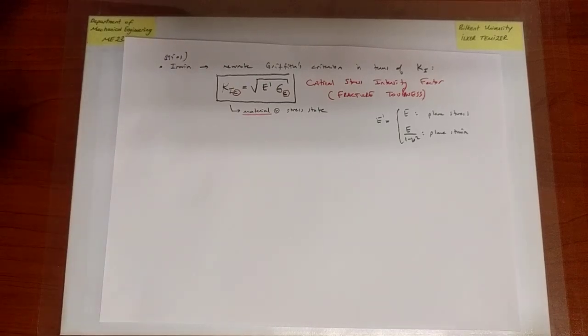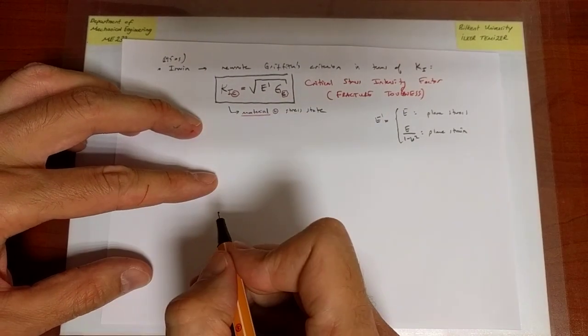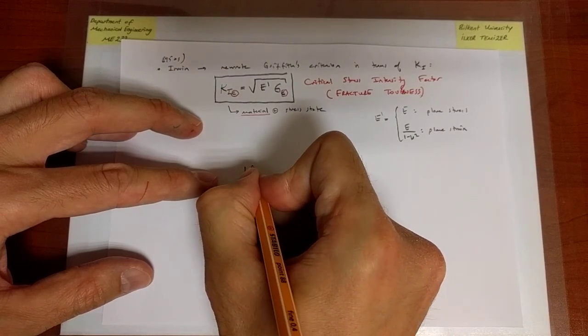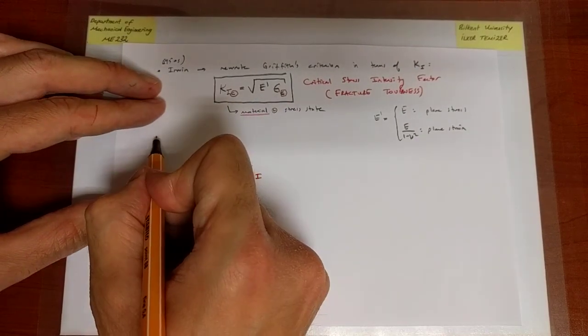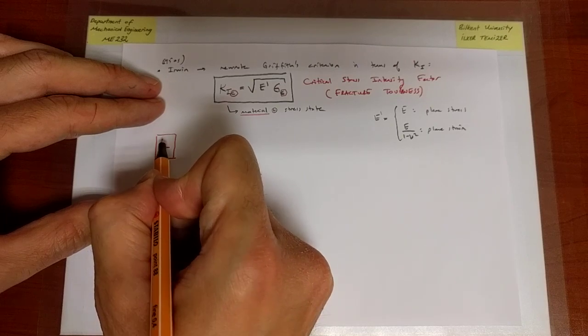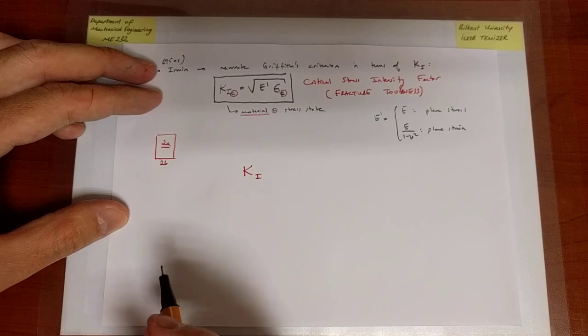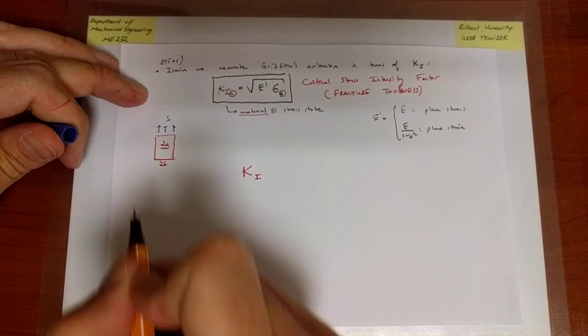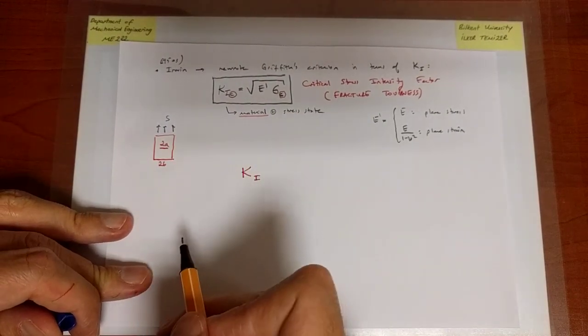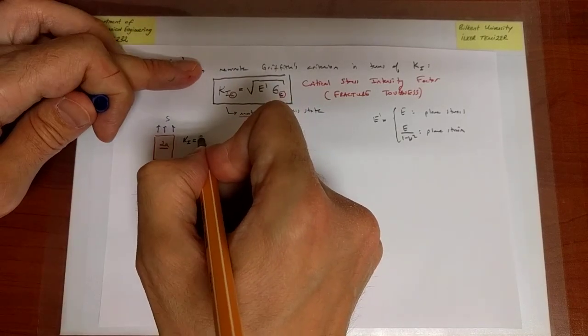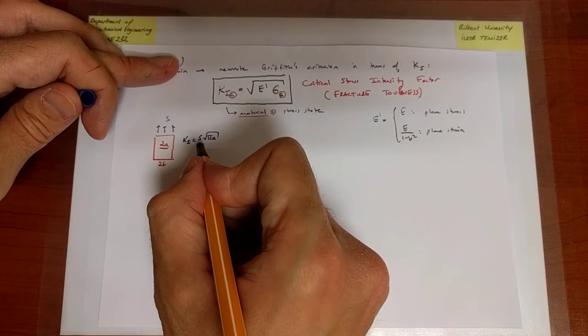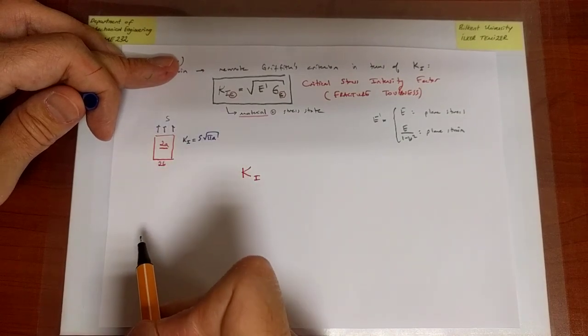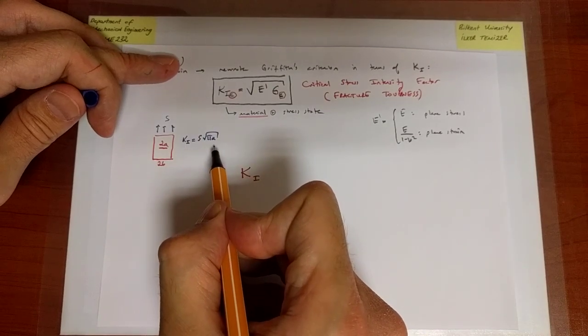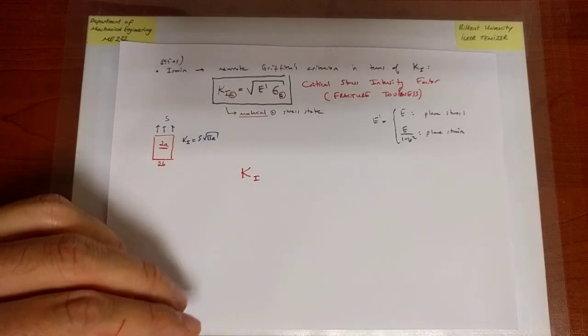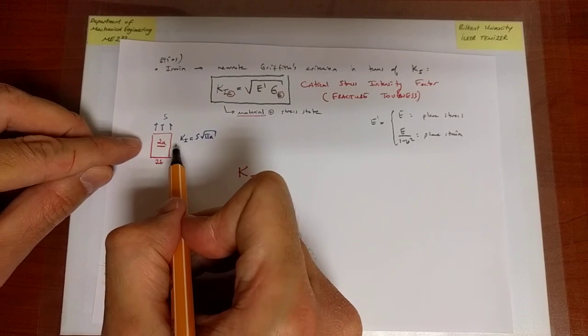So now, what Irwin said is, would you like to predict whether or not fracture occurs? Very simple. You give me the structure, and for that structure, eventually I will be able to calculate the stress intensity factor. It is K1. Let's say we have a plate, and there is a crack of width 2A in a plate of width 2B, and we are pulling on this plate with a certain far field load. I know exactly what K1 is at any stage of loading. So I know the value of A and I know the value of S. I can calculate K1, and I keep increasing S. As I keep increasing S, the value of K1 will keep increasing. But there is a certain critical value of K1 that is needed for this crack to propagate catastrophically and break the structure apart.